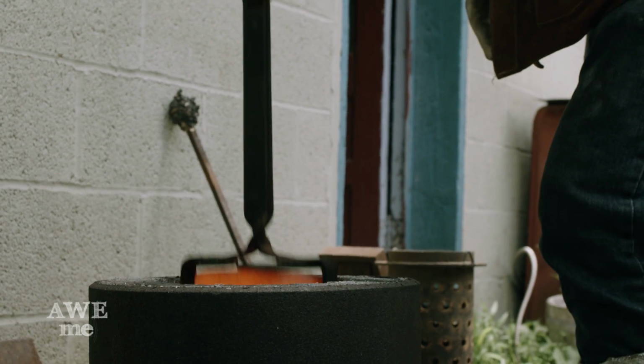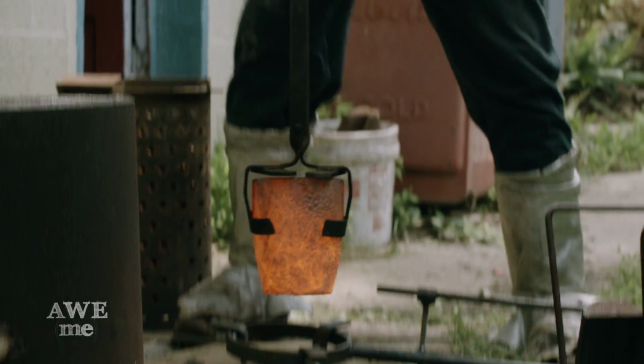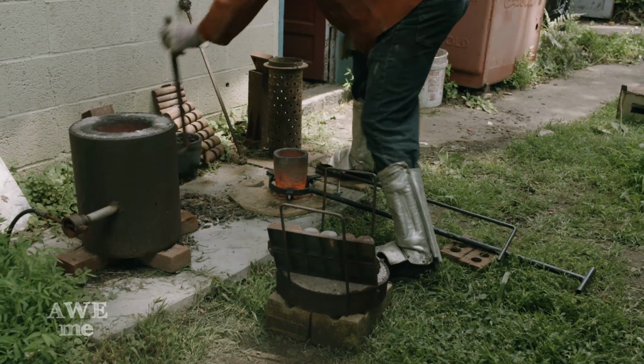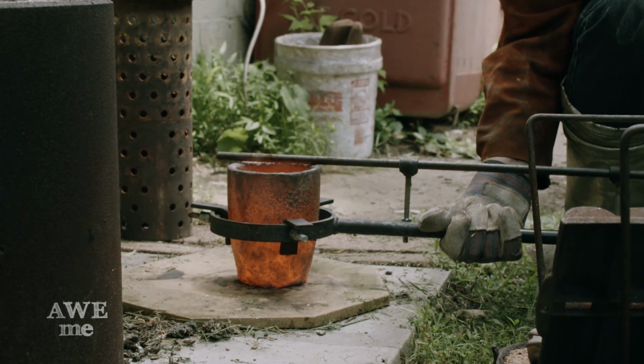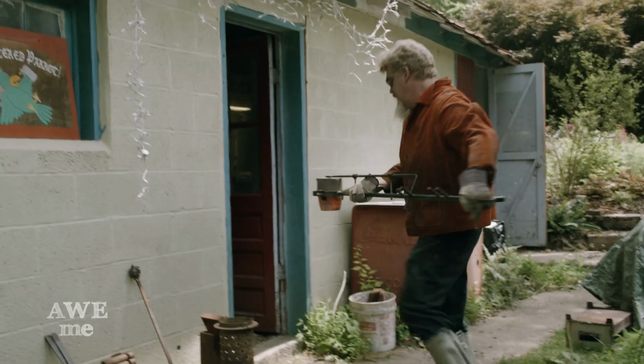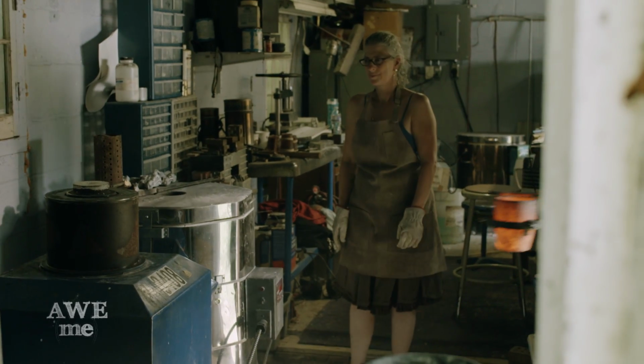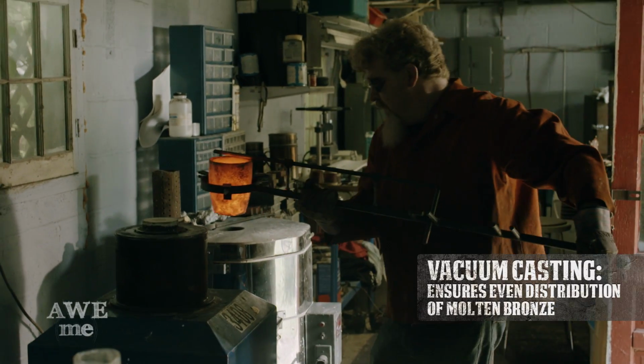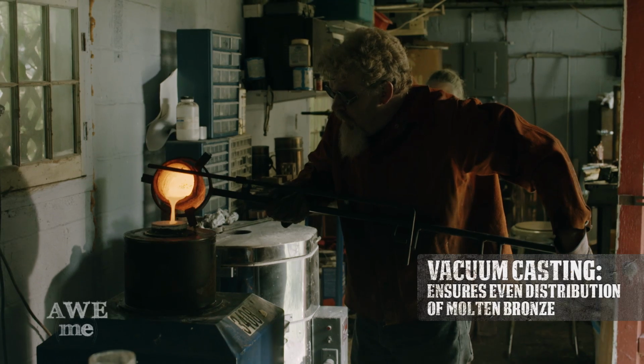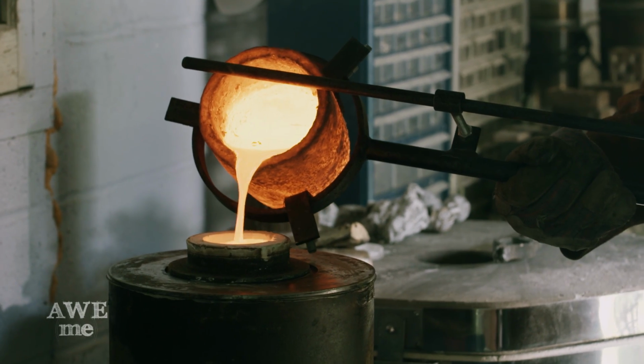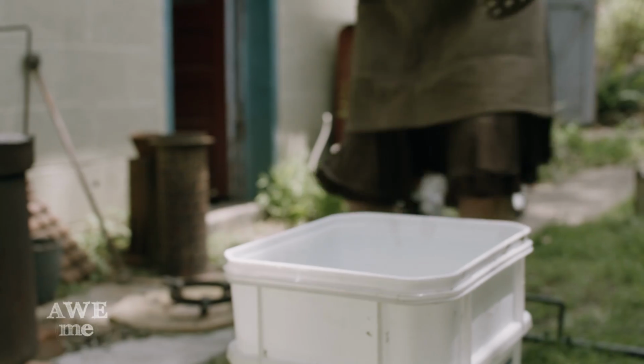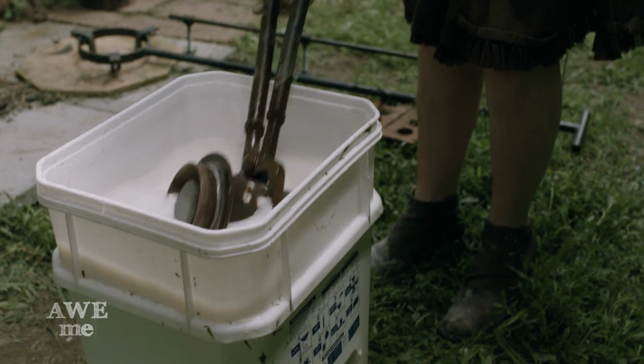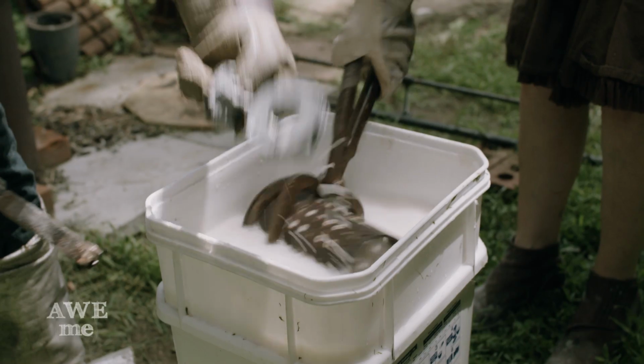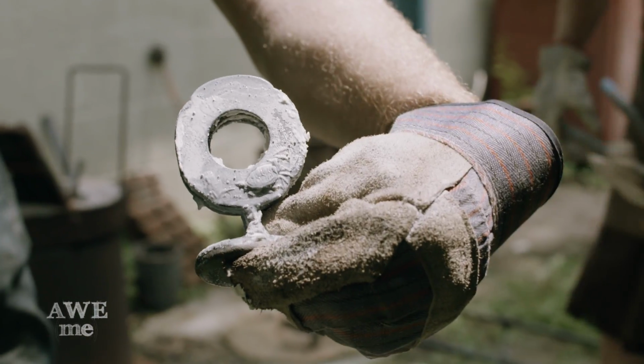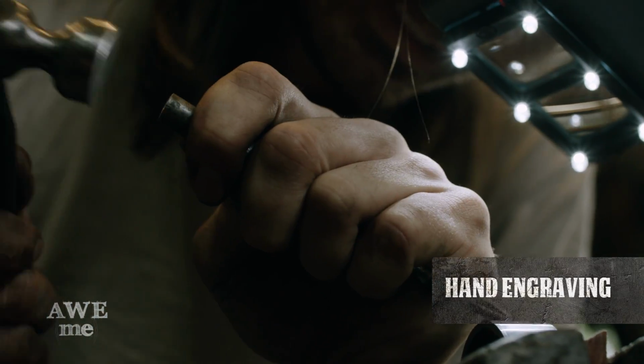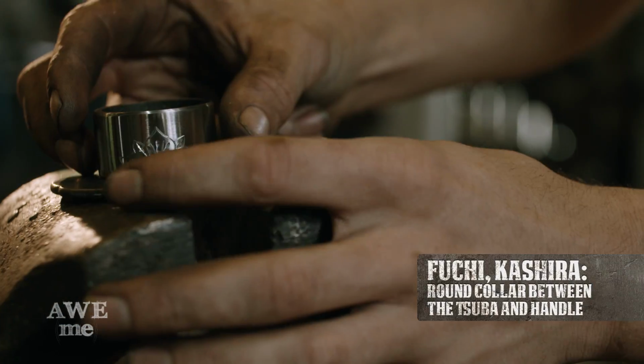I'm pulling the crucible out of the foundry, setting it in the shank, which will then control the pour. When we have a big crucible, we have a 2-man shank we do from both ends. Carefully carrying the 2100-degree bronze, I enter the shop, turn on the vacuum machine, and pour the bronze. Once the metal temperature has fallen below 900 degrees, we quench the flask in water to remove the plaster. To add a little extra Japanese flair to the piece, we have Ilya hand engrave some flowers on the fuchi and kashira.